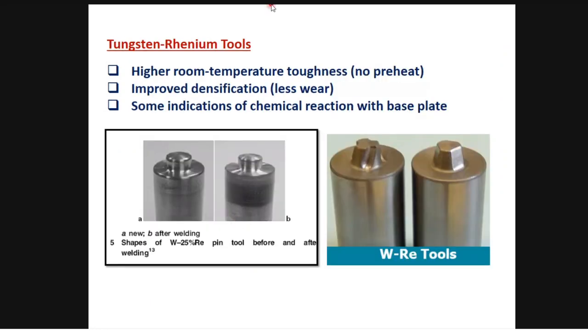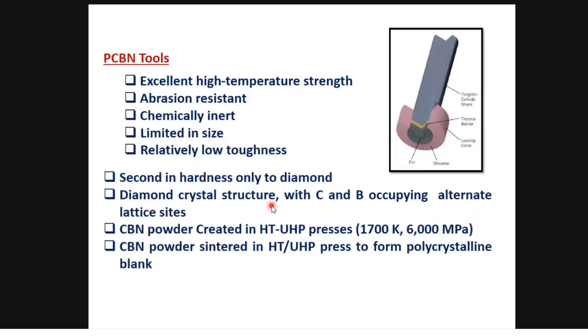So then they go for alloying. Tungsten rhenium is one alloy tool that is able to withstand the high temperature application. This is one. A is new, B is after welding. And tungsten rhenium hafnium carbide is another tool material that is also used for this purpose. But the PCBN tool is an excellent tool because it has excellent high temperature strength and abrasion resistance, and is chemically inert. It will not react with the surrounding or the base metal. It is limited in size and has relatively low toughness. That's the one problem, relatively low toughness.